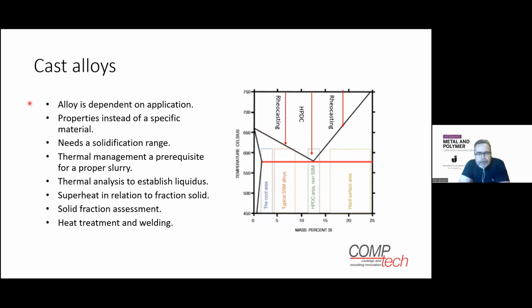What's important when you do Rheocasting is that you make a thermal analysis to establish where you have your liquidus temperature. And then when you set up the process, you set the superheat in relation to the fraction solid that you need, so you get a very stable process. You need then to assess the solid fraction that you get from your settings in order to be able to reproduce this and so on. So the alloy needs to have in general a lower amount of silicon in order to get a good solidification range. We usually talk about under-eutectic alloys because that's the most common, but it's also possible to go on the over-eutectic side as well, though not so common.